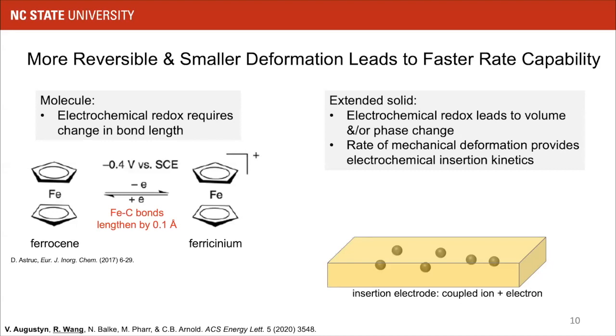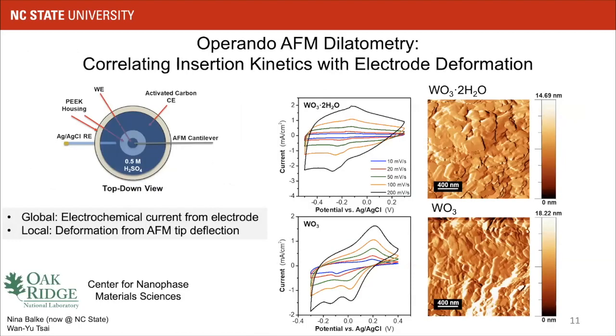They're much more significant because of this extended nature of the materials. And you can consider using the rate of mechanical deformation to provide insight on the electrochemical insertion kinetics. This is that fundamental coupling between the extent of charge storage, the extent of volume change, and the rate capability of the material. To probe this, we used operando AFM dilatometry. This is an ongoing effort with Nina Balke, who is now at NC State, and Wan-Yu Tsai, who's at Oak Ridge National Laboratory, where we basically used the AFM tip as a dilatometer.